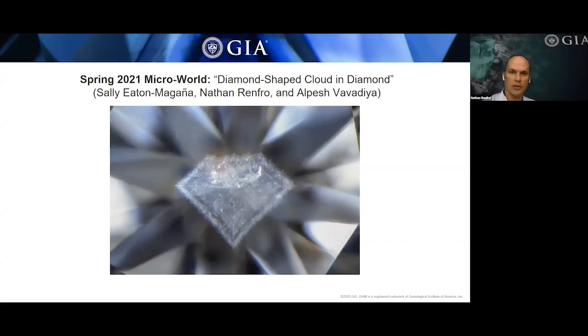We also had quite the novelty diamond that was examined by myself and other GIA authors. Inside, just under the table facet of the stone, there was a hydrogen cloud which resembled the profile view of a diamond. So we have this stylized appearance of a faceted diamond inside a faceted diamond. That was quite an interesting inclusion. This hydrogen cloud mimics the cubic crystal structure of the diamond. However, one of the corners was truncated, which is where the appearance of the table facet is.